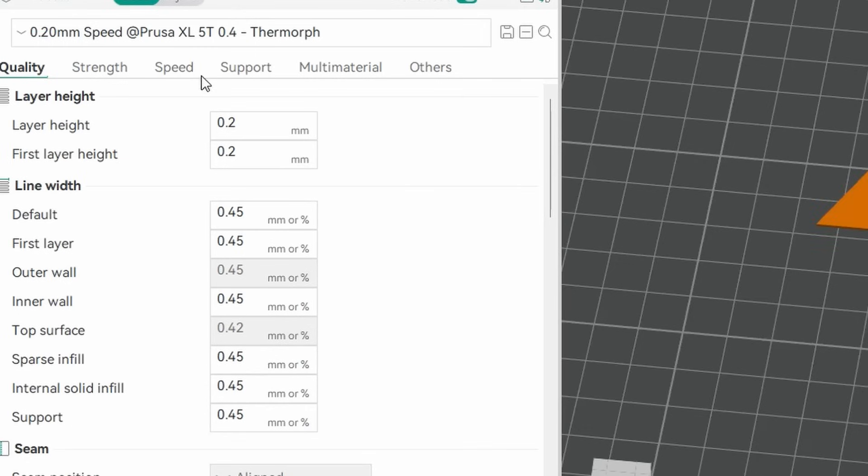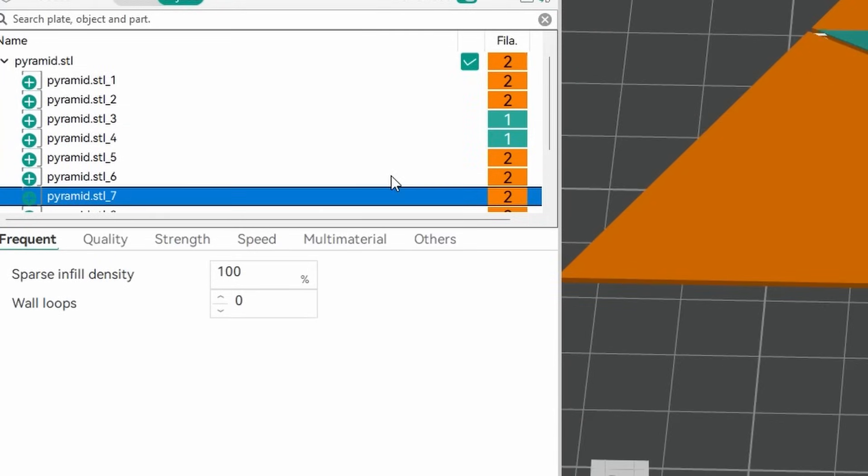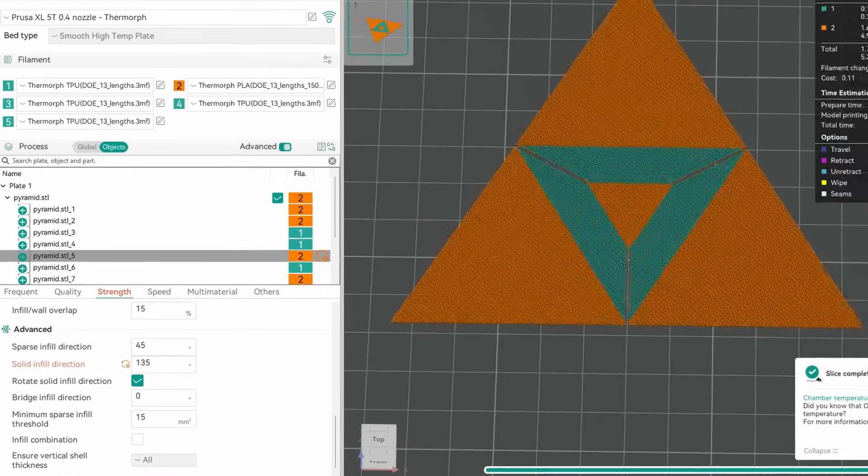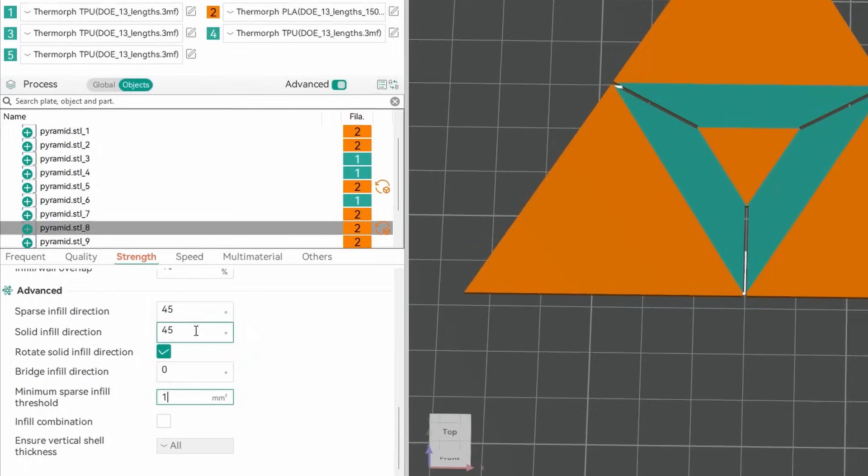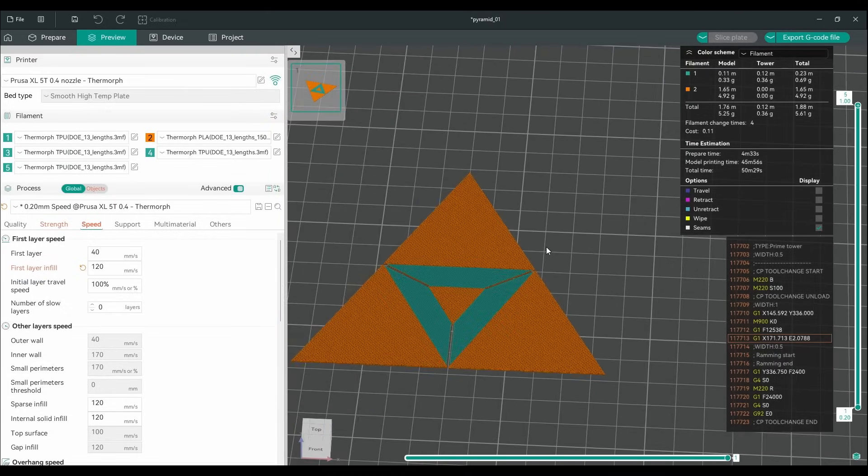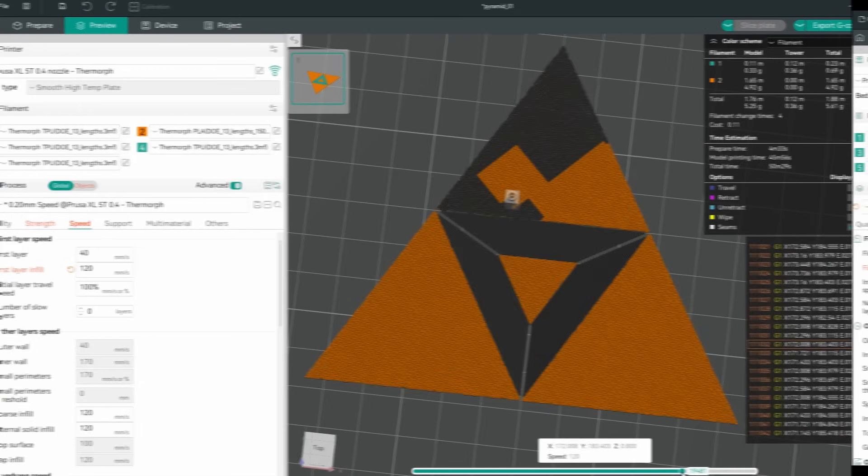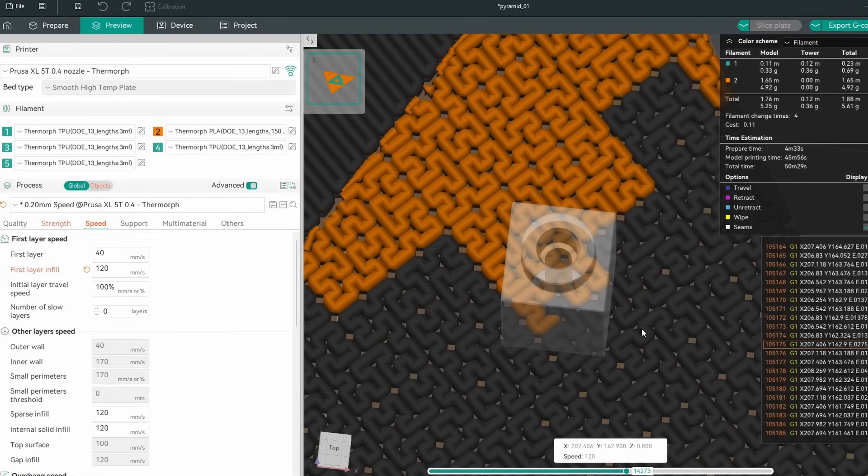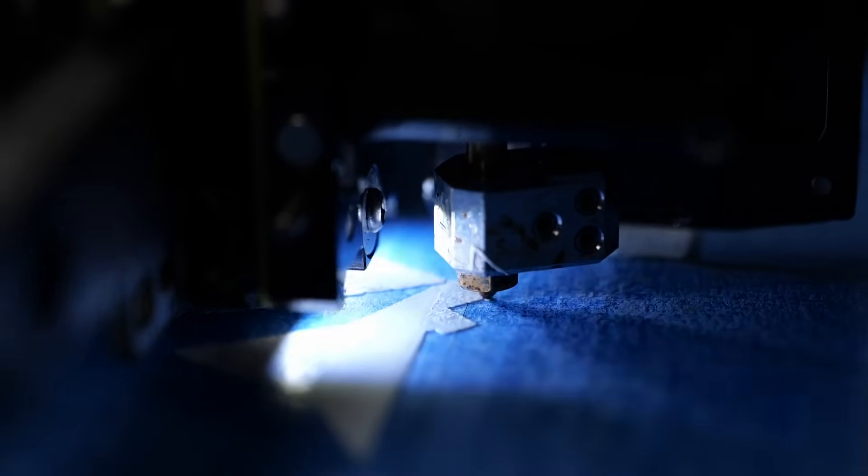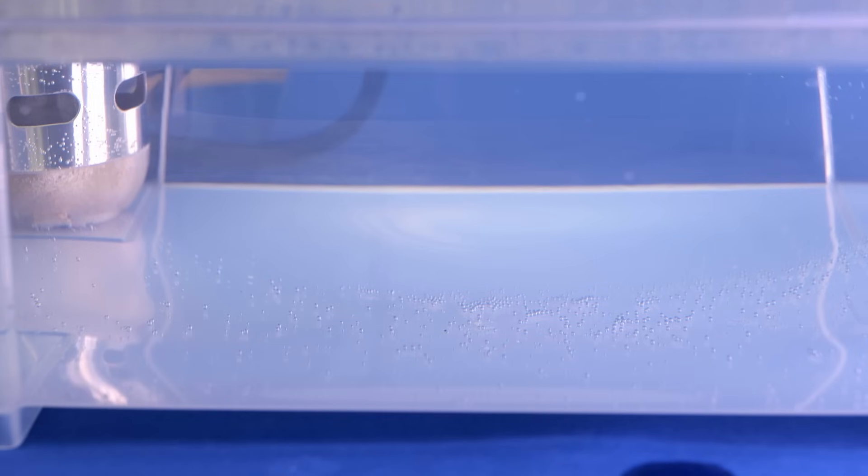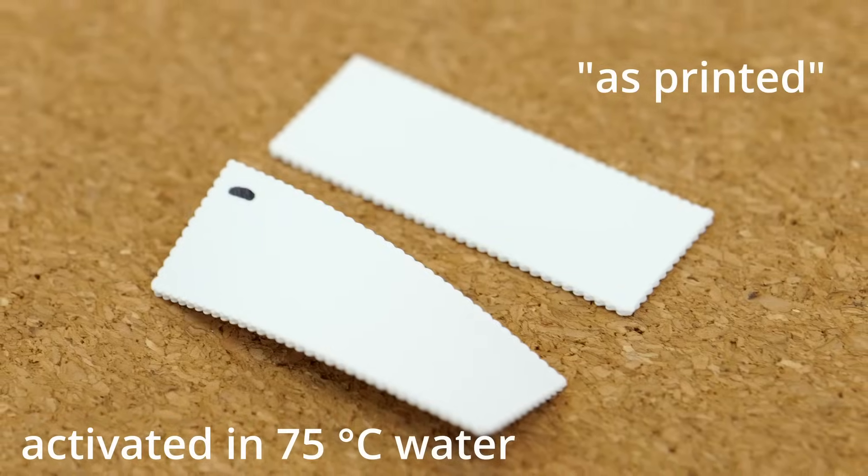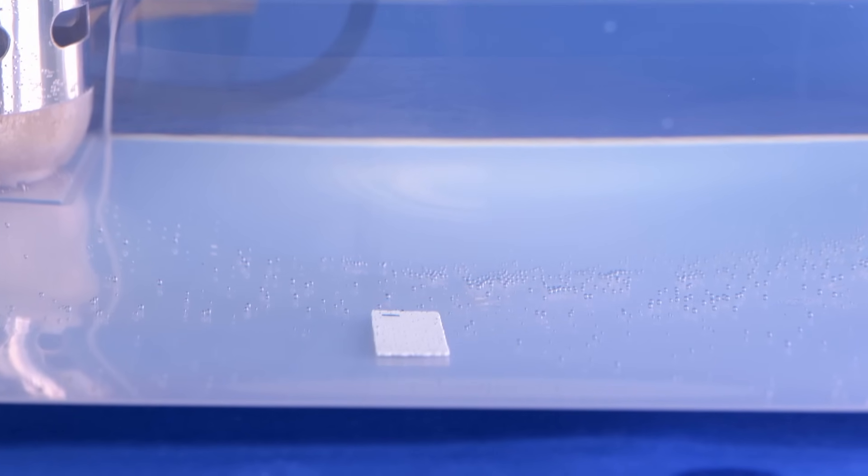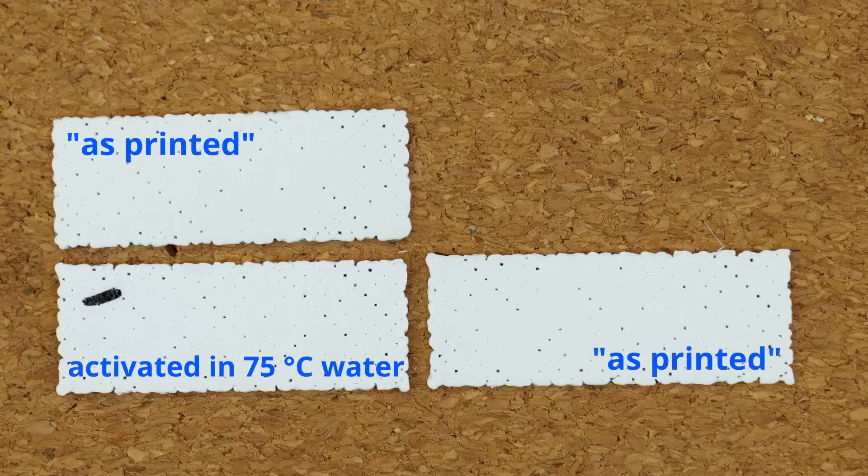The first step was to split the single STL into individual parts again to apply different parameters. First, I assigned the materials to the individual components. Most are usually PLA, while the constraint layers are assigned to the TPU profile. Then it became a Sisyphean task to assign all the appropriate printing speeds and infill orientations to all of the remaining actuator sections, resulting in a finished sliced file where we can observe all the individual settings we applied at work. You might have noticed that I used Hilbert Curve infill for the sections that I want to keep flat. Because of the numerous short print moves in every direction, which also lead to a relatively low speed, this type of infill generates only minimal internal stresses. If you print flat plates with standard rectilinear infill, they will still warp or significantly shrink during heat activation, which can disrupt our model. The flat areas printed with Hilbert Curve infill shrink only slightly and also do not warp, making this infill great for passive flat sections.